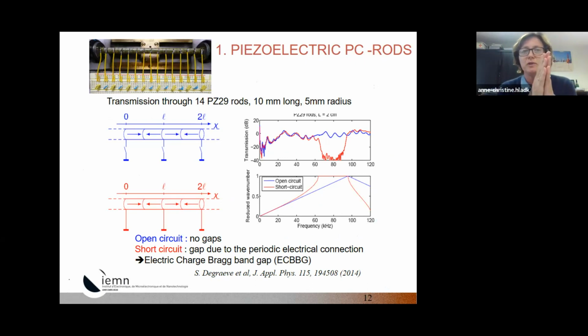Then here is the experimental evidence of the electric charge Bragg band gap. You see we have here a stack of 14 PZ29 rods, 10 millimeters long, 5 millimeter radius. We apply an excitation on the left, and we see the transmission on the right. First, all the electrodes are in open circuit. In that case, the propagation is like in a homogeneous material, and it is the blue curve here, and the transmission is quite constant over the whole frequency range.